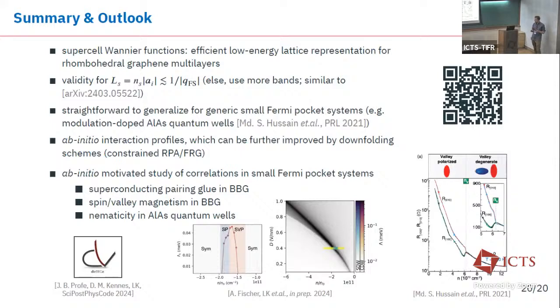One point is that this kind of modeling is very straightforward to generalize for any kind of small Fermi pocket systems. Actually, graphene is a difficult system to start with because you have those chiral quasiparticles to work with, and you have to be careful to include Berry curvature, etc. correctly. They're topologically non-trivial. There are other systems that are easier, and one example would be modulation-doped aluminum arsenide quantum wells, where you have very tiny Fermi pockets in the conduction band, and those can also be represented by supercell Wannier functions. And then you have a very interesting phase diagram of nematic states and symmetric phase states that have a transition at a certain electron density in the system.